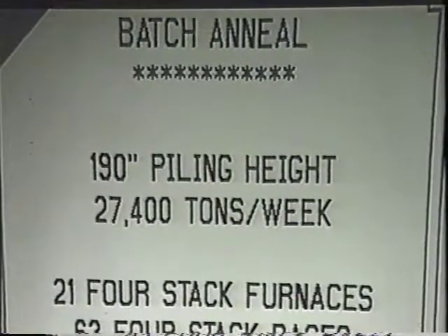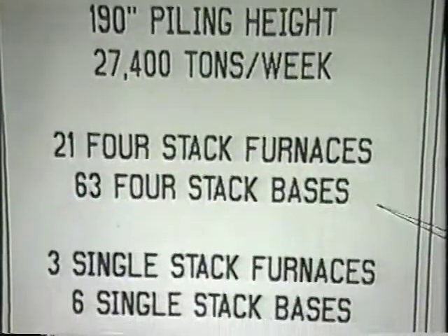Just a couple things about the batch anneal facility. We can pile to 190 inches high. So depending upon your coil width, we can get 2, 3, 4 coils on top of each other. We have 63 bases. That's where we're putting the outer covers. We do have some single stack furnaces, meaning we can heat just one stack of steel as opposed to 4 stacks of steel. And we'll utilize those for some specialty cycles, such as our high-strength cycles, so that you don't have to wait for 300 tons of steel to come along before you can anneal it. So for those cycles that don't have a lot of volume, we'll do a single stack as opposed to a 4 stack. And throughout the batch anneal facility, we use a rail car system to transport our steel.